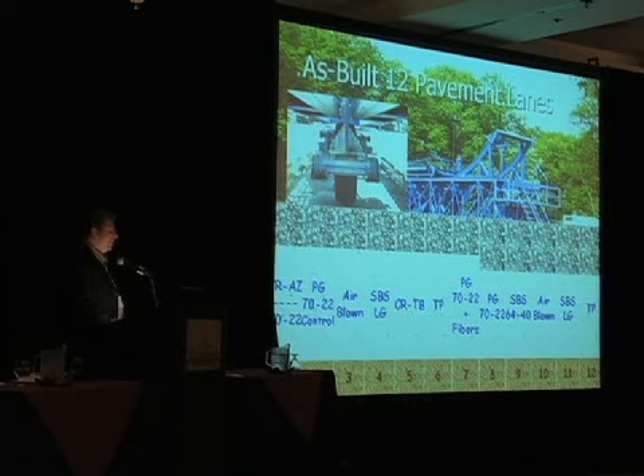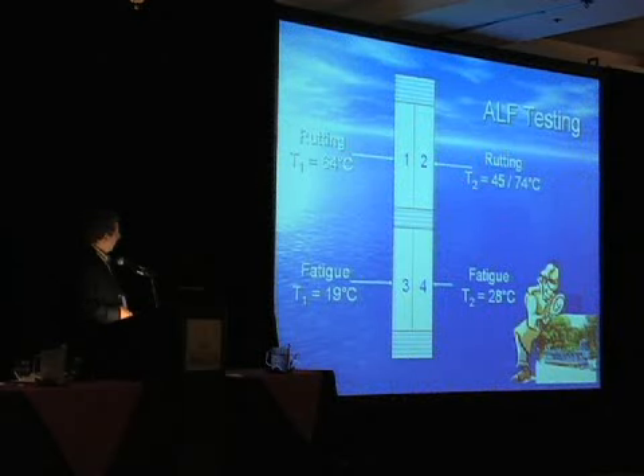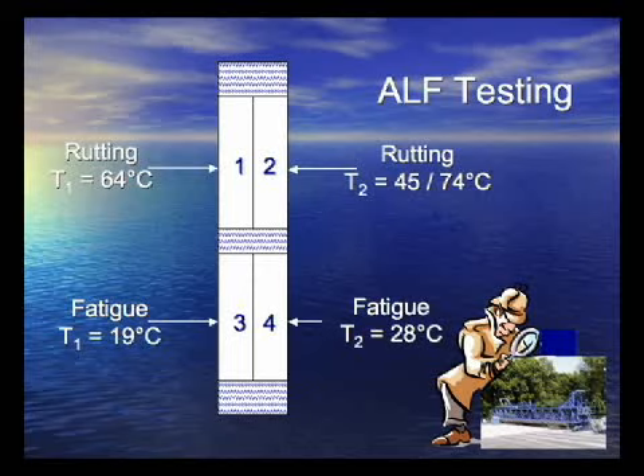This was found to be the most damaging tire, so a lot of accelerated load facilities use this tire. It provides about 40% more damage than standard duals. In each test lane, we have an opportunity for 4 tests. In the lower sections, we do fatigue at 2 temperatures. And in the upper section, we have rutting. We are targeting 64 Celsius.